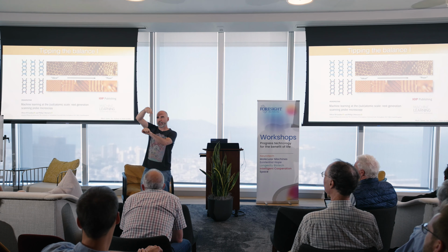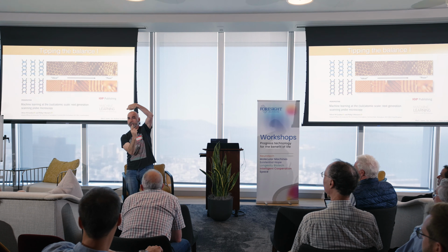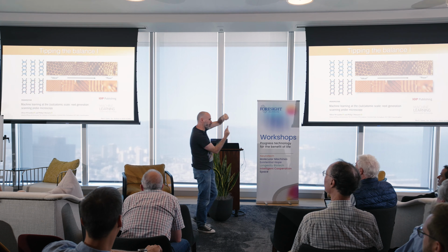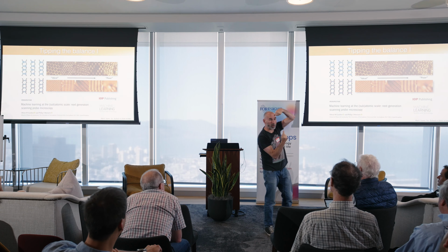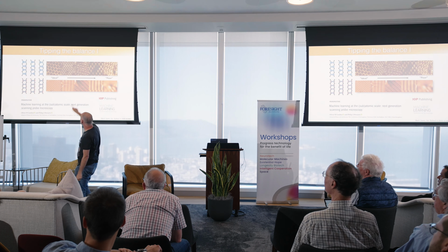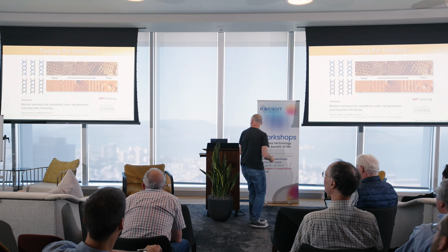So typically in STM, you think you have something sharp imaging something less sharp at the surface, but that, of course, by symmetry is exactly the same as that. So if you have something sharp, such as an electron orbital with a relatively small spatial extent, which is the case for the dangling bond orbitals at the silicon surface, this will image this. And that's what's going on here. We can tell from that central image we've got a dimer terminating our tip, or something very much like a dimer.